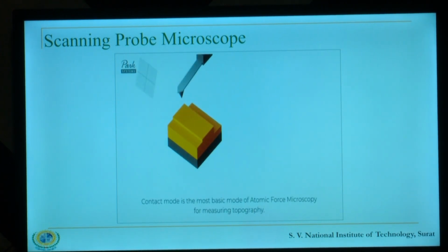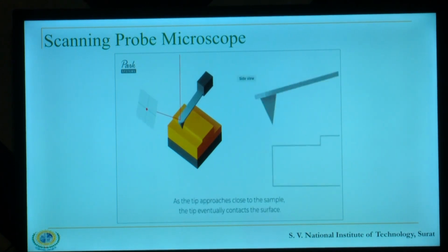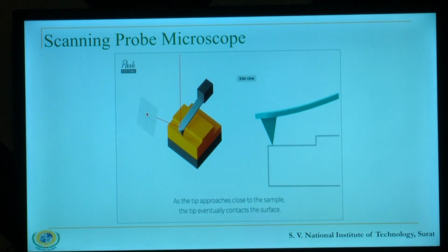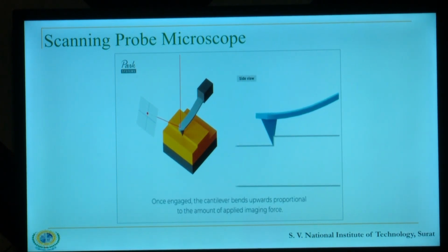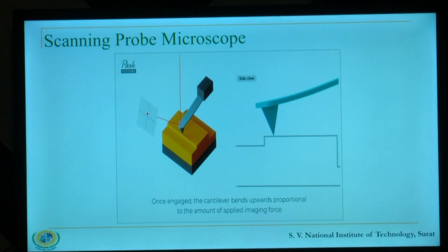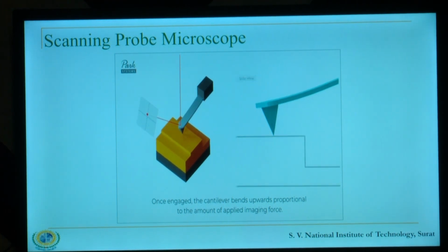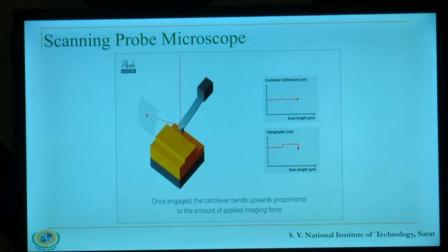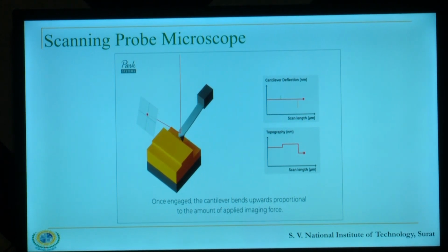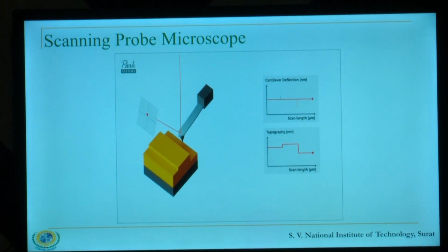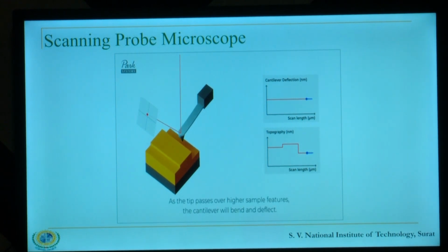Contact mode is the most basic mode of atomic force microscopy for measuring topography. In this mode, the cantilever scans while applying a constant force onto the surface of the sample. As the tip approaches close to the sample, the tip eventually contacts the surface. Once engaged, the cantilever bends upwards proportional to the amount of applied imaging force.